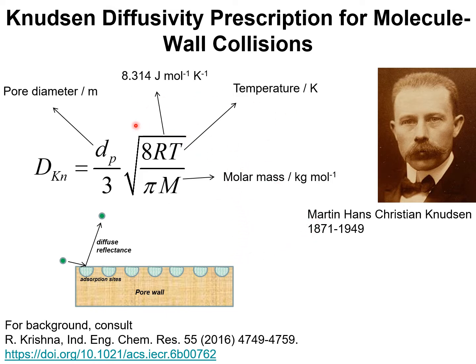The formula is applicable provided the gas molecule undergoes diffuse reflectance on striking the pore wall. It is not applicable, as we shall see later in this presentation, to components that adsorb more strongly and have a bias to move along the wall.